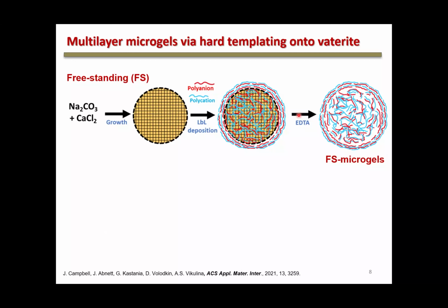Then at the next step, if you add, for instance, EDTA, you get rid of calcium carbonate and you end up with basically an inverted replica of those calcium carbonate particles, which is what we call microgels. So now they are porous inside, and where you have the empty space inside, this was the space previously occupied by calcium carbonate. So here I call them freestanding microgels. This means that now you can't see any surface here.